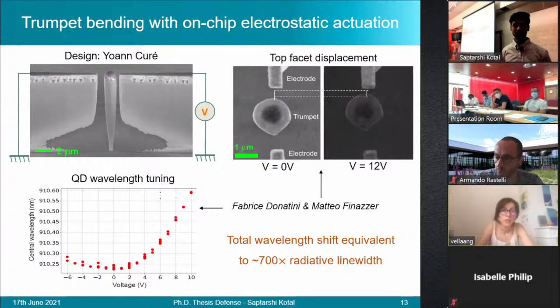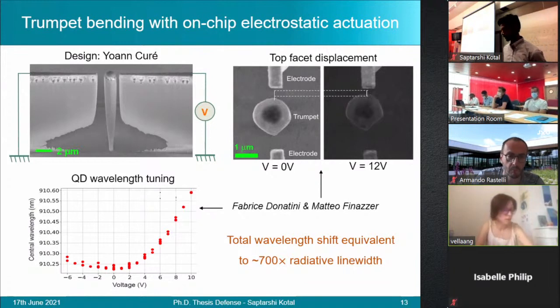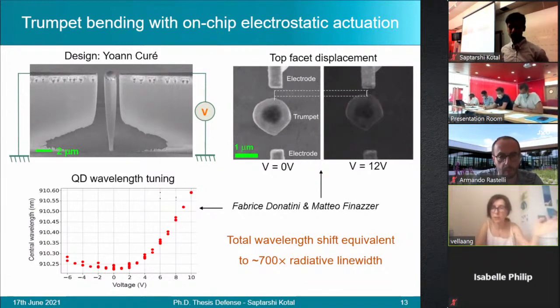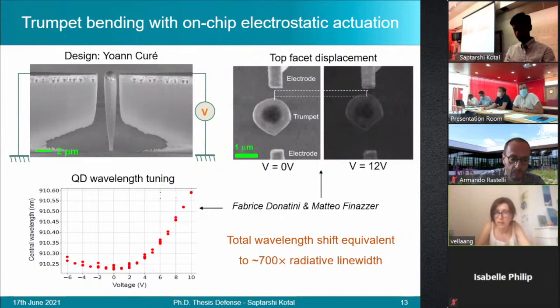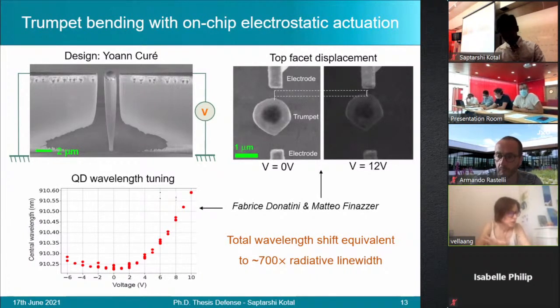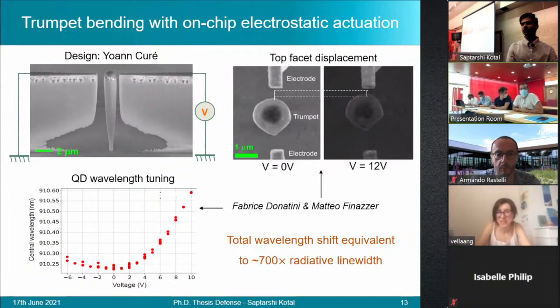In the optical shift, you have less, but if you go from the optical shift to the shift in the X position, because there is a formula in your manuscript to calculate the mechanical shift from the optical shift, it corresponds to a shift of 5 nanometers, something like this. And from your calculation, you expect 2 nanometers, so it is not so far. Yes. So I think within the order of a few nanometers would be fine. Okay.